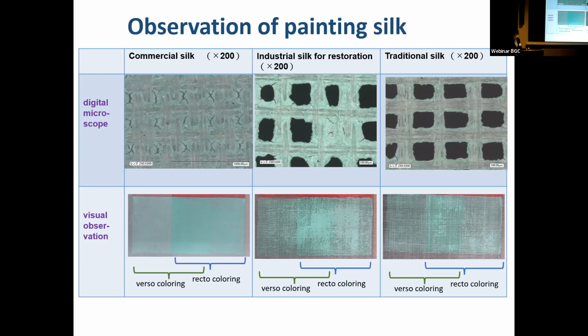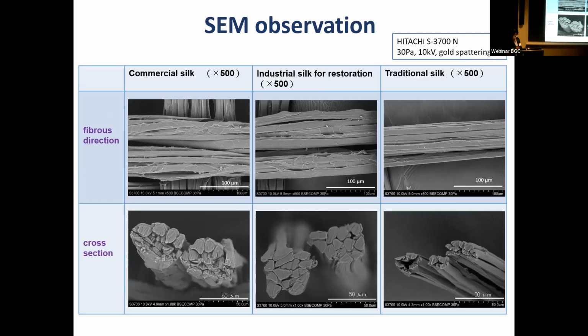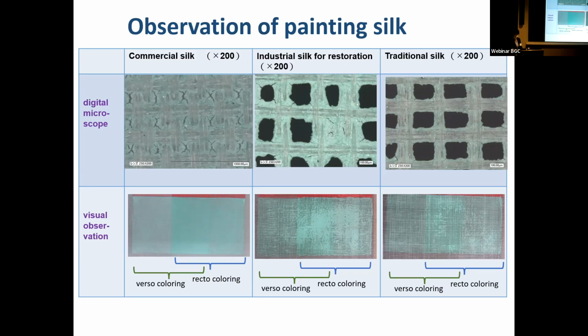This difference explains why it's hard to match the color of the infilled part to the original painting in conservation, and furthermore, why the infilled color seems to change when the viewer moves, owing to the different reflection angle between them. In addition, fiber shape appears to influence transparency, because traditional fiber was thinner than modern fiber, like this. This might explain why verso coloring is more effective in traditional silk and perhaps why the technique is no longer